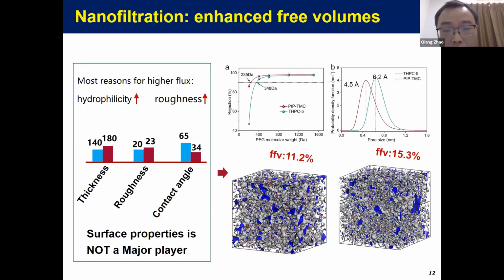So what is the reason? By using cutoff experiments, we found that the membrane mean pore size increases from about 4.5 angstrom to 6.2 angstrom. That is, the membrane becomes looser. And by simulation, we show that the FFV, the fractional free volume, increased from 11% to 15%. Both results point to a speculation that the membrane becomes looser with larger pores and more pores because of the surface modification by these strong ionic monomers.